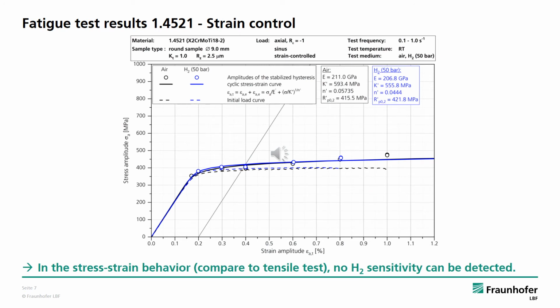Strain-controlled tests were carried out on these unnotched specimens and the results plotted in the form of the stress-strain curves. Here you can see the results in black for the tests in air and in blue under hydrogen. Compressed hydrogen with a pressure of 50 bar and purity 5.0 was used for the investigations. In addition to the results of the cyclic stress-strain curve in the form of the solid lines, the initial stress curves are also shown as dashed lines. The material is slightly cyclic hardening but does not show any susceptibility to the hydrogen based on these tests.